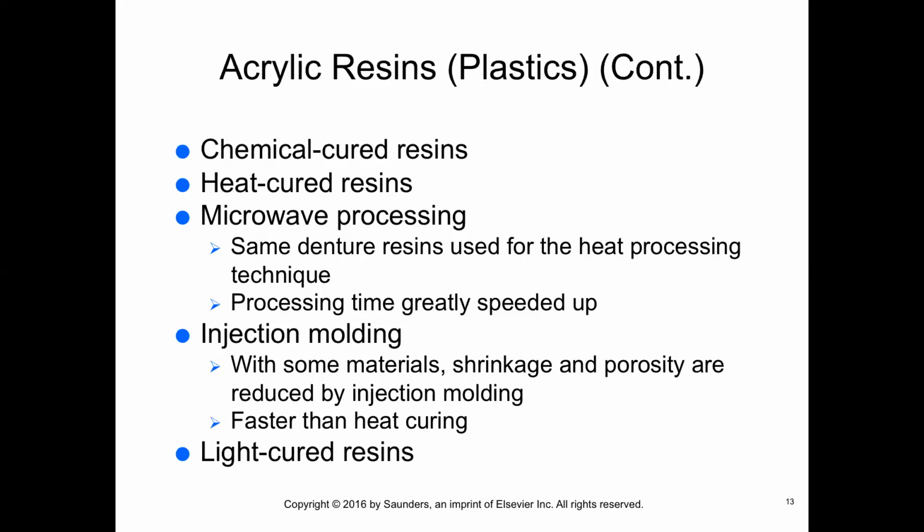Polymerization of chemical cured acrylic resins is set into action when the tertiary amine in the liquid activates the benzoyl peroxide in the powder to produce free radicals. The hydroquinone initially inhibits the reaction from progressing by destroying the free radicals and increases working time so that the materials can be manipulated for a reasonable period of time.